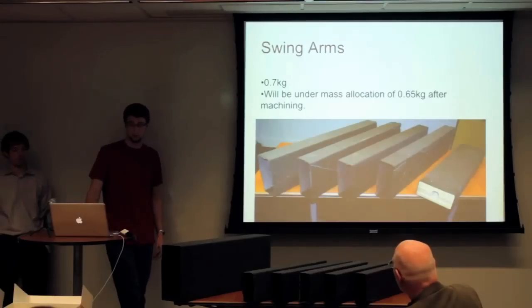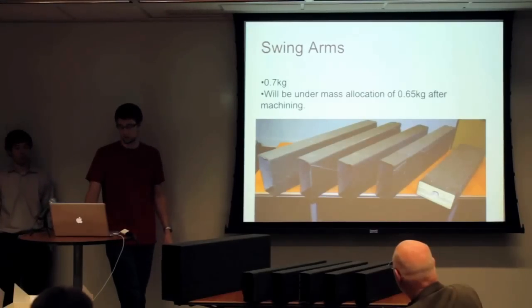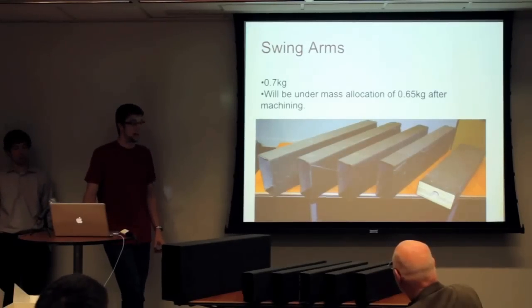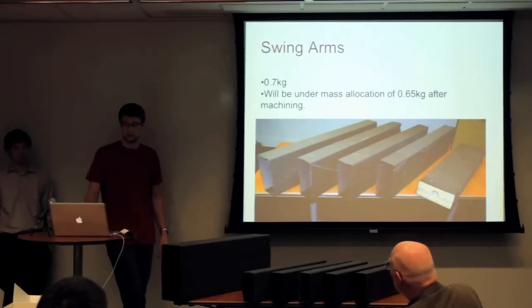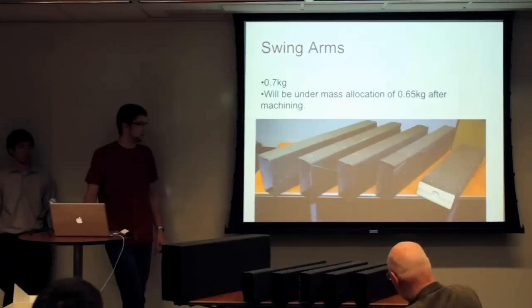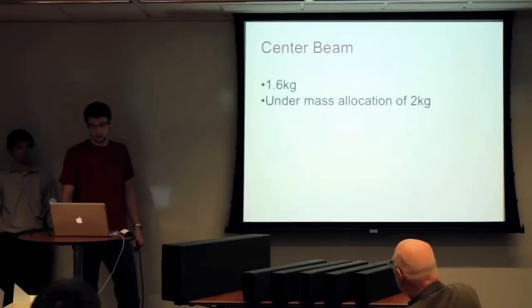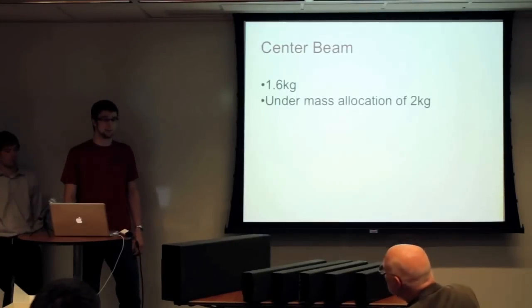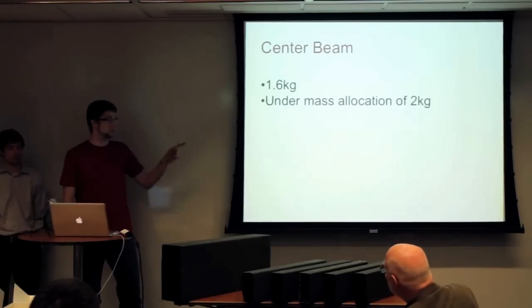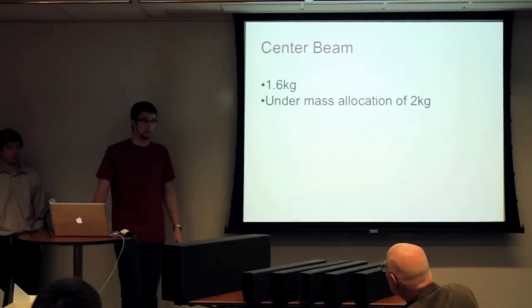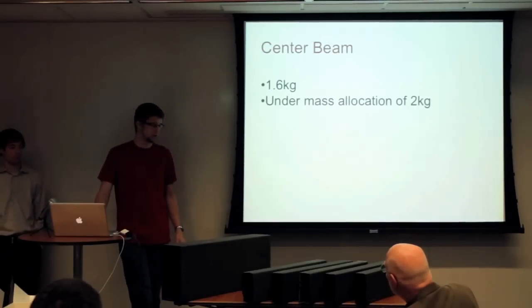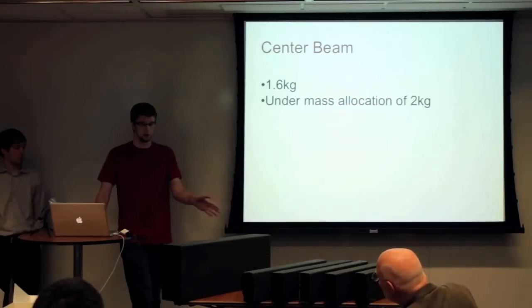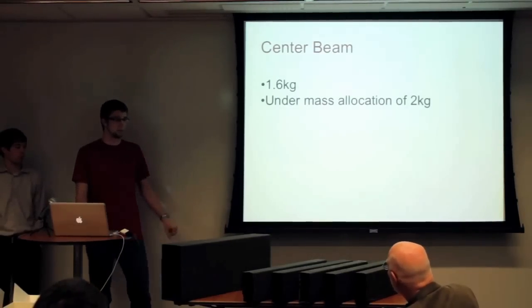So we have the four swing arms that are done, and the fifth one that we tested to failure. They're weighing 0.7 kilos each, and we have a mass target of 0.65 kilos. But these are all longer and heavier than they need to be because they still need to be machined. So once we machine them all, we're aiming to be under our weight target. The center beam was a big surprise. We calculated it would be much closer to the 2 kilogram load. It weighs 1.6 kilos and a few small ones, and it's not even machined yet. There's going to be 4 inches cut off of this, so we're going to be way under our mass.